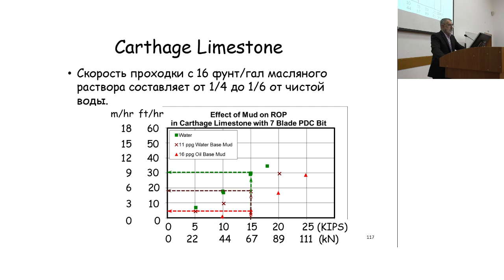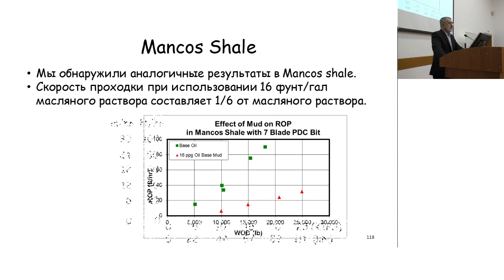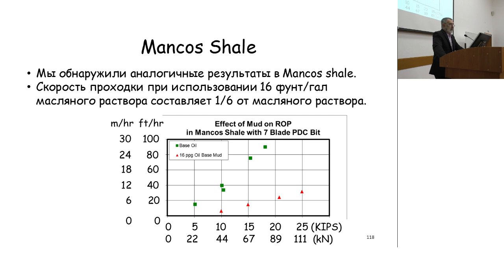So you'd say, well, why don't we just always use water because it drills faster? Well, the answer is the water would flow into the earth, as I said, and we have a problem because we need to keep the fluid in the borehole. So we make our muds so that they form these filter cakes on the wall of the hole, and that's for a good reason, but it also turns out that the mud has an adverse effect on the drilling, as shown here. This is similar data for another kind of rock, Mancos Shale. We're comparing the base oil with the oil weighted with weighting material. For the base oil at 67 kilonewtons, they got almost 24 feet per hour, but by weighting it up, making the mud heavy, it's only about 5 meters per hour.